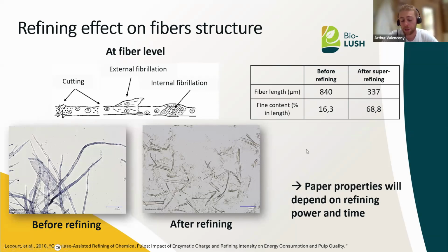Two parameters that we can analyze during refining are the fiber length, which will considerably decrease, for example here from 800 to 300 after super refining, and the fines content, which represents the elements between 5 microns and 200 microns, that will considerably increase, and it will improve the bonding between the fibers. The paper properties will depend on refining power and time. If we want to improve properties, we can increase the refining, but at one point, if we increase refining too much, the fibers will be too short to have good mechanical properties. So we need to find the right point to have the wanted properties for the selected application.